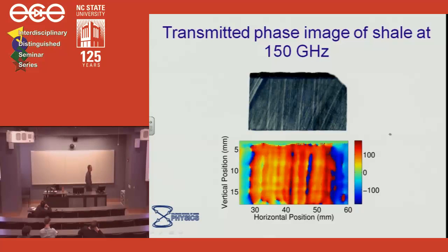It's very important, for example, in oil shale. I have a lot of colleagues in Colorado interested in that because there's so much oil shale. Oil has a very low dielectric constant. So just by doing these dielectric measurements, we can measure the organic content of rocks much more easily than the traditional way, which is called pyrolysis, where you just burn off the volatiles.